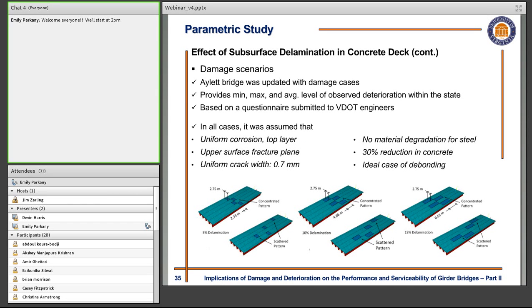For each of these levels of propagation, we selected to have 2 different patterns, the concentrated pattern and the scattered pattern. And within these 2 patterns, we actually included the random nature of delamination into our analysis. Regarding the modeling, we assume delamination occurs as a result of uniform corrosion in the top layer of reinforcement. So as a result, we didn't consider any degradation in the steel material.